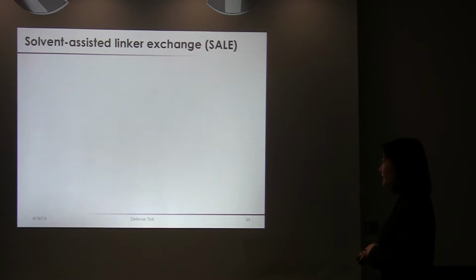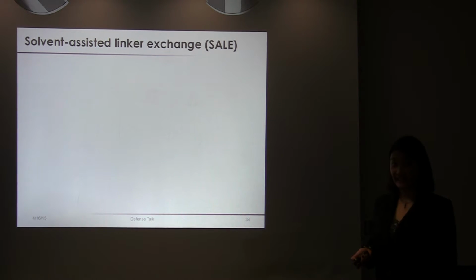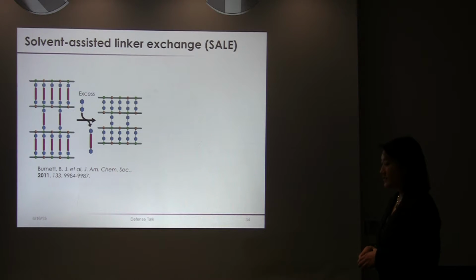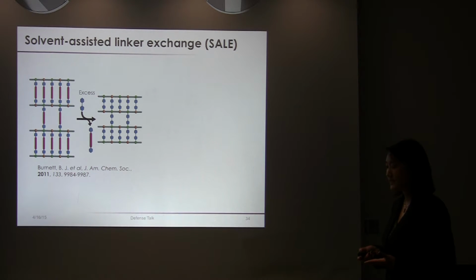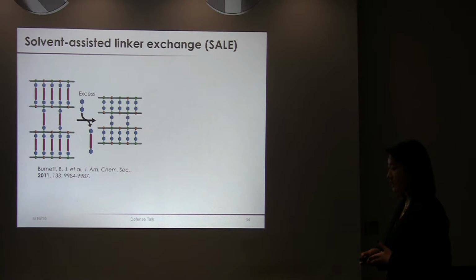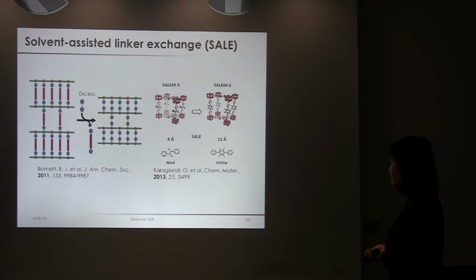And closely related to PSM is what's called solvent-assisted linker exchange, or SALE. And SALE essentially works by exposing the parent MOF to excess amounts of replacement daughter linker. And this occurs by ligand exchange and not so much dissolution and recrystallization of the MOF. And consequently, the topology of the parent MOF is retained. And so SALE has definitely been pioneered by Burnett and his coworkers, as well as our group, on specifically these pillared paddle wheel MOF systems.